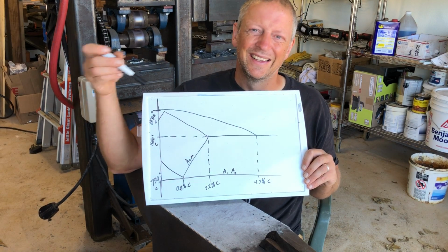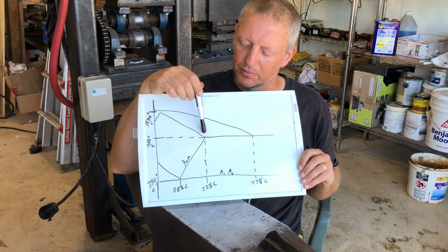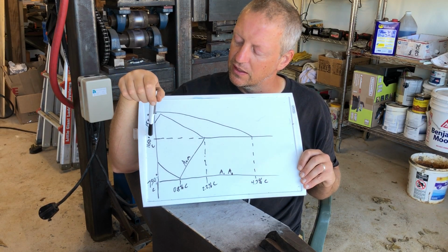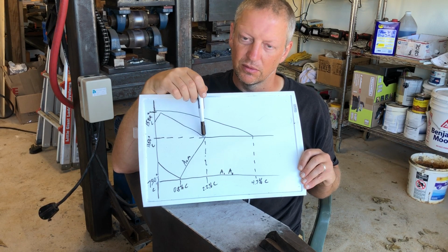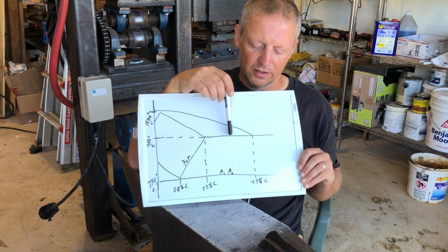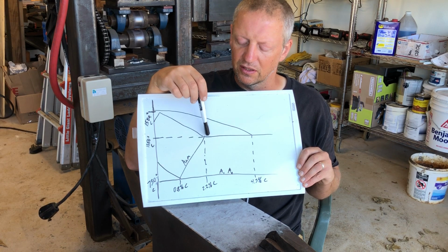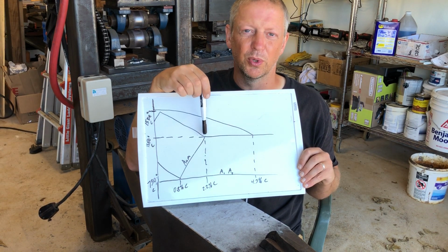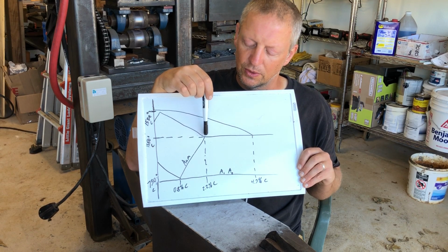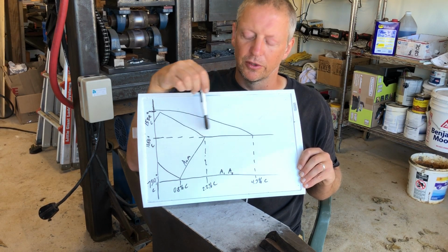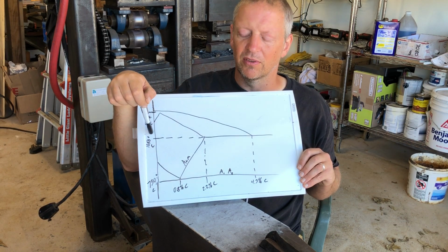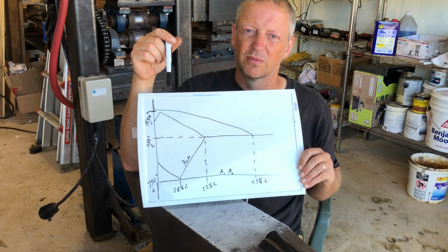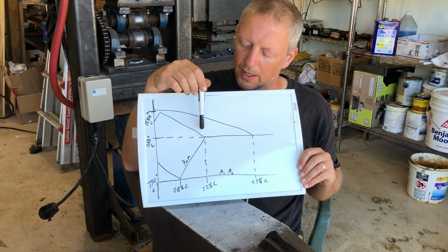So, another key point on here from the perspective of Wootz is this right here. So here we are at 1150 C, roughly. Now, for all of this section out here, that is the top end of your forging temperature. So once you get past 2.2% carbon, you're absolutely limited by 1150 C. This is in the orange range, the brighter end of the orange range.